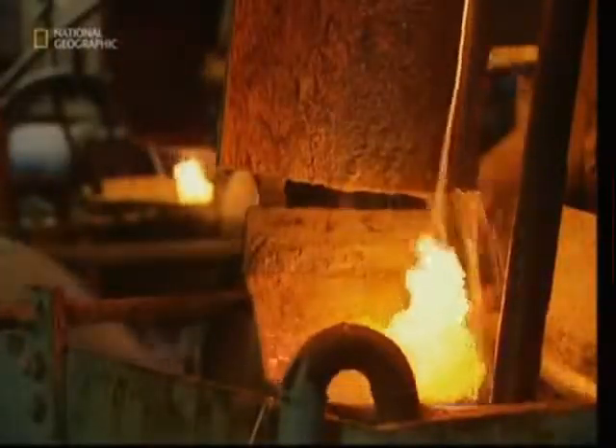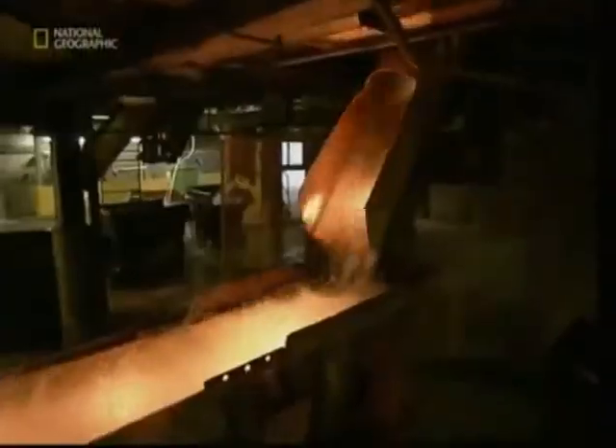In the second chamber, chlorine gas is pumped through the molten liquid. It absorbs impurities and carries them to the surface, making the surface layer unusable for now — but it isn't wasted. This layer is diverted out of the furnace and plunged into water to cool it down.